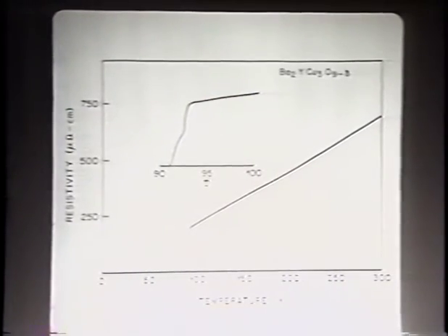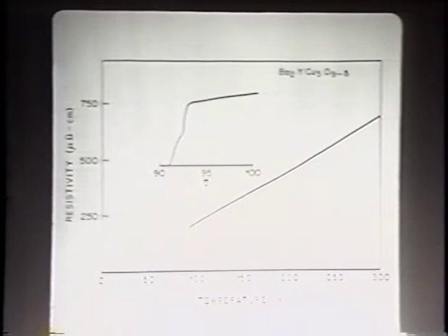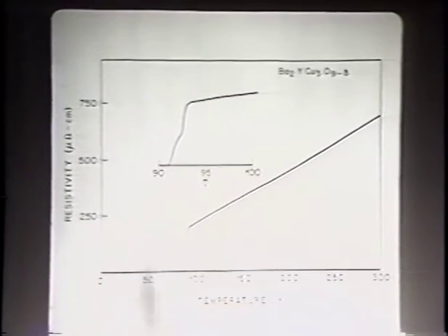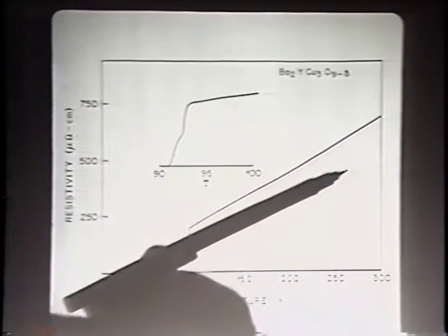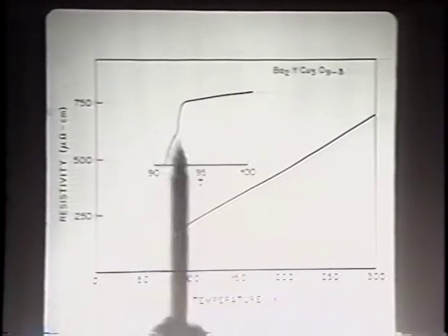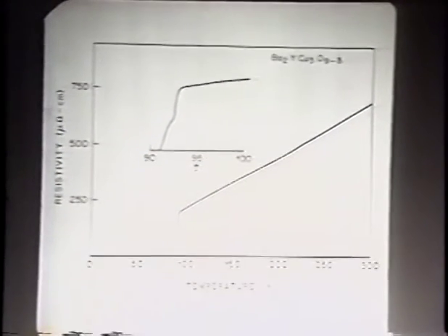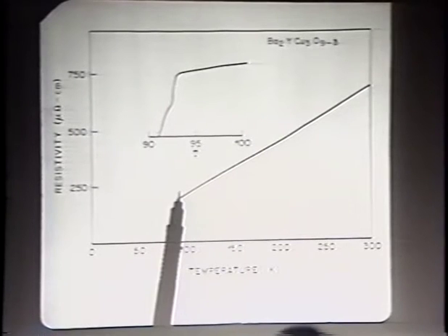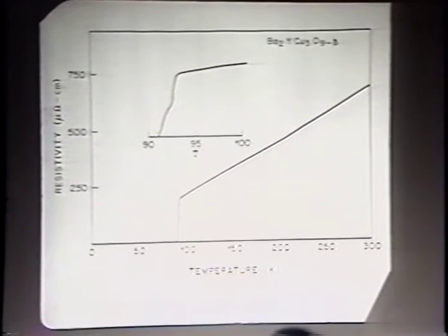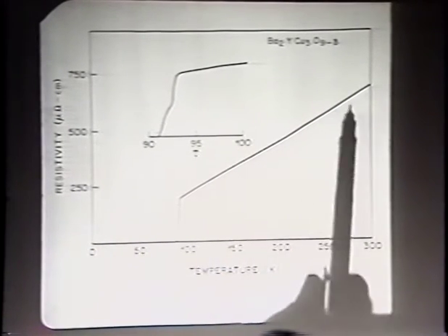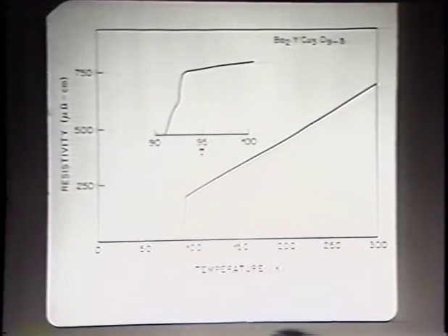So instead of showing all the various view graphs, I just flash this one resistance curve. On this resistance, I would like to point out one particular thing. It is the normal state behavior, which is quite unusual. First of all, it is quite a good material if you extrapolate down there. It's a damn good metal. Not only, of course, does it go superconducting there with quite a narrow transition width in itself, but also this linearity in resistivity has not only been observed in this material, but also in the lanthanum-strontium copper oxide and in the barium-lead bismuth oxide-based single crystals. We never published that, but we have them. So there's a commonality in these oxide superconductors.